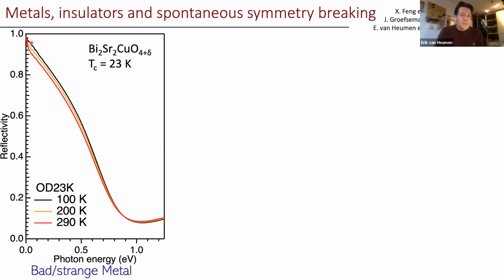And here you see basically the frequency dependence of what is a metal. For those of you who remember from the Drude model what the plasma frequency is, you can almost read it off here. The plasma frequency is the minimum in the reflectivity, so it's around 1 electron volt in this case. It's not exactly the plasma frequency, but that's a detail. You can see that this is a metal because the reflectivity extrapolates to 1 at 0 frequency. For a metal, if you measure the reflectivity, you would expect a reflectivity very close to 1 and at 0 frequency exactly equal to 1.